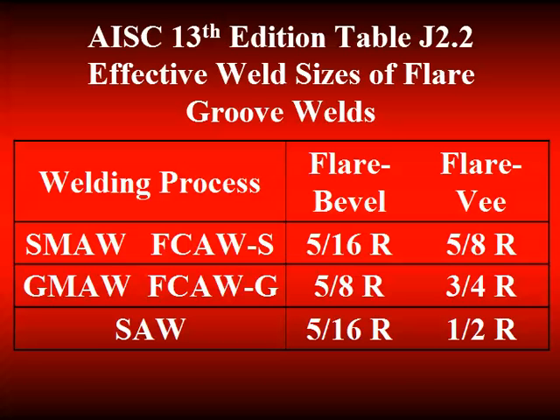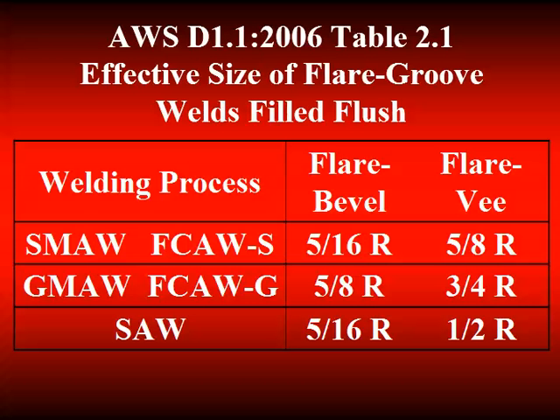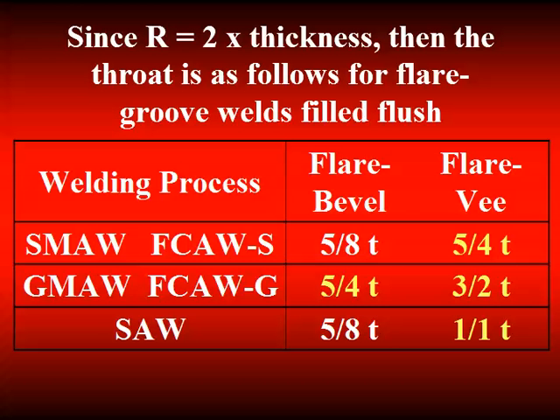Oh, this is the same table from AWS. We got coordinated this time, and they're both the same. If I combine the general trend that the radius is twice the thickness of the material, then I can combine those two and look at the throat that again is a function of the material. And what's very nice here, as I show in the yellow, these are all the joint details now that give me full capacity that matches T. So here I have actually 5/4 T, 5/4 T, 3/2 T, and down here 1 T. So now I'm developing the full capacity of the connected material with those joint details in those processes.